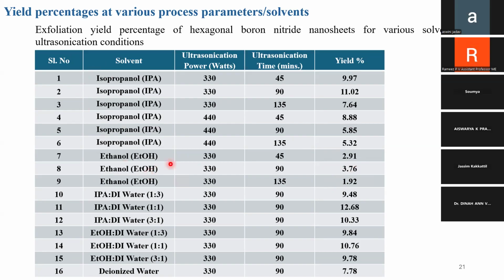So I used isopropanol for my further study, where I prepared the co-solvent in these ratios: 1:3, 1:1, 3:1. And I took ethanol just as a reference. So 1:3, 1:1, and 3:1. You can see that IPA and DI water at 1:1 gave me the highest yield percentage. So these were my experimental trials, where I changed the ultrasonication power and ultrasonication time and got several